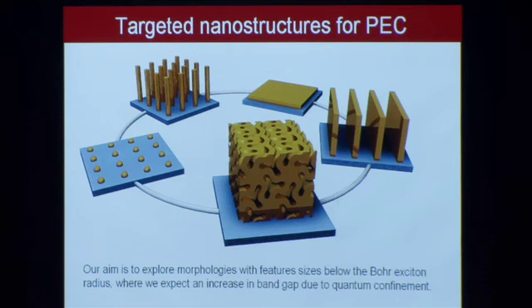Otherwise, it's tough to understand the optoelectronic properties of a given size of the material. Although this is great to start off the study, in the end, we'd like to look into other morphologies that we think are more appropriate. And the reason why I say that is because if you imagine 5 nanometer nanoparticles of moly sulfide sitting on a surface, if you shine light onto that, how much light are you really going to absorb in a 5 nanometer nanoparticle? Not all that much.